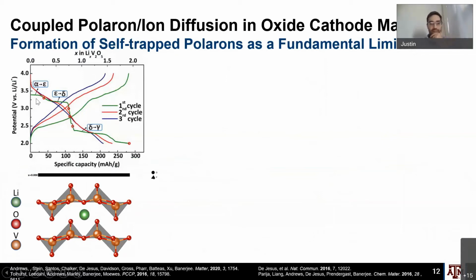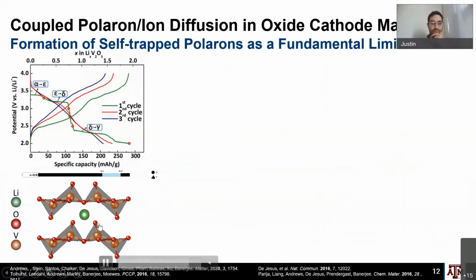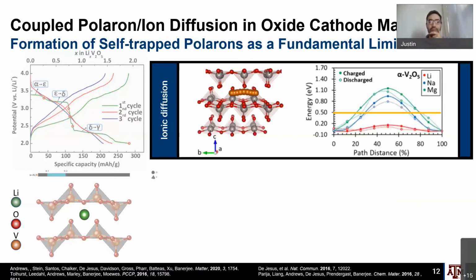So basically this is a discharge curve for these. You can see this is the alpha to epsilon and epsilon to delta, and then delta to gamma. So this is the irreversible phase transition. And just to give you an idea of how the structure evolves a little more, as you can see here, now we're entering the epsilon phase, and what's happening is very subtly these oxygens are puckering towards the lithium and sort of coalescing around that lithium and trapping it in place. And so this is kind of what's happening here.